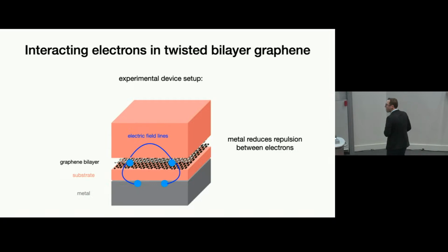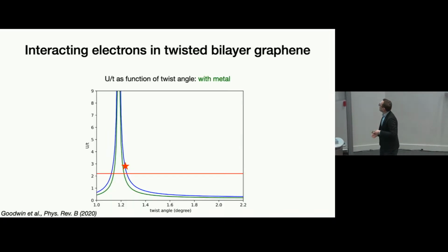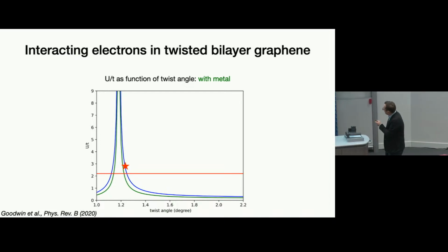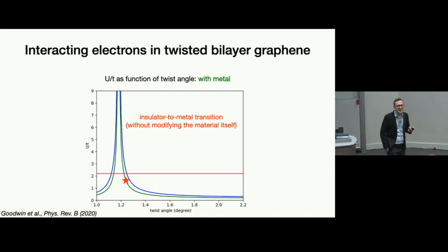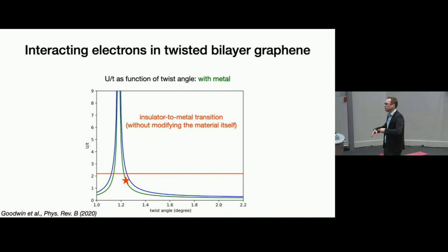So we redid our calculation, taking now into account the effect of the metal, and then we got this green curve here, and it looks similar, but there are some differences. In particular, one thing that can happen is, let's say you're at this particular twist angle here, and if you don't take the metal into account, you think the material is an insulator. But when you do take the metal into account, it's actually a metal. And that is something quite surprising, so you can transform the material from an insulator into a metal without moving its atoms or without changing the wave function or anything like that.